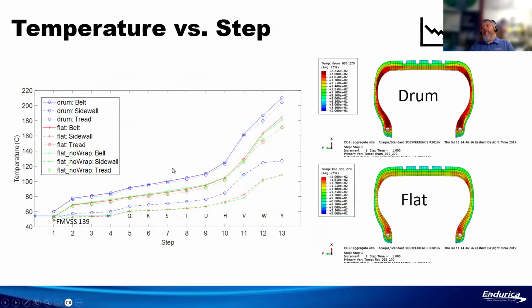So in these types of problems, it's often very important to look at the thermal effects, right? If we're thinking how temperature influences things, then we need to calculate self-heating, which we can do. This is just showing temperatures in the simulation as a function of the test step. You can see that in the first 9 steps, increasing the speed does increase the temperature, but once you hit the standing wave, the temperature just shoots way up.